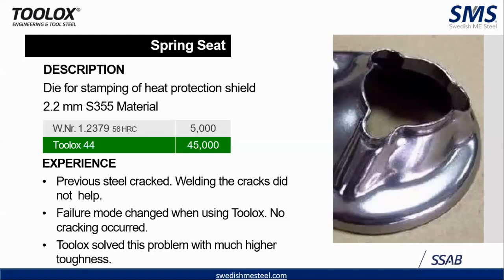This is a die used for stamping a heat protection shield, 2.2 mm of S355 material. The previous D2 failed at 5,000 components due to cracking. So the previous steel cracked. Welding the cracks did not help because the carbon equivalent is low in D2. The failure mode changed when using Toolox, and no cracking occurred. So it not only helps in better manufacturing time, costing and heat treatment, but with all the problems that you face while tool making: your chipping, your cracking, your edge retention problems, your deformation. And it also gives a new perspective on the designing front itself.